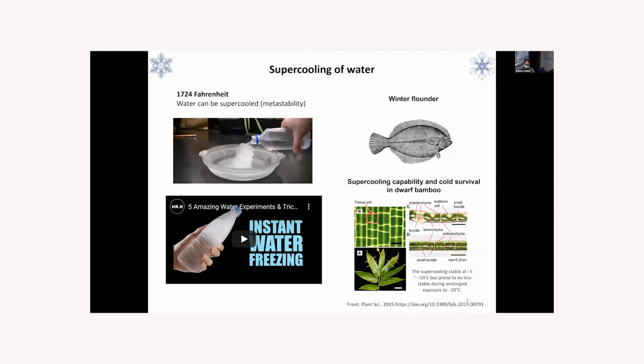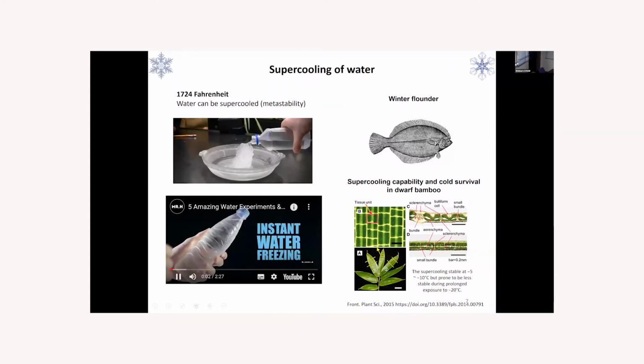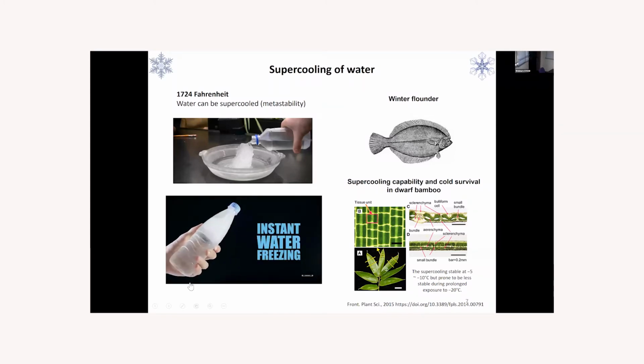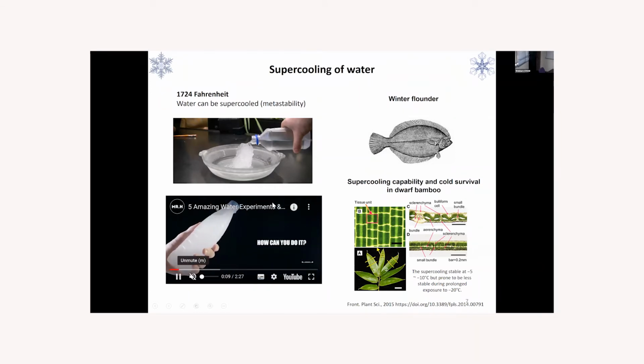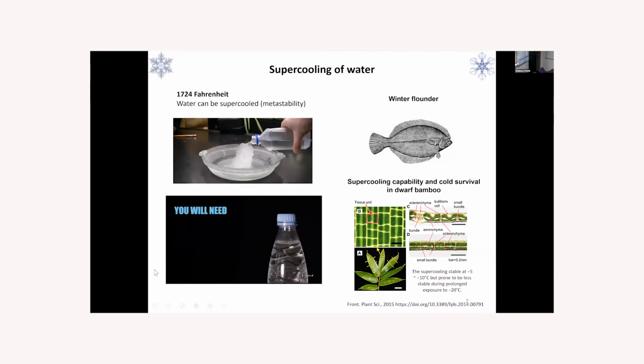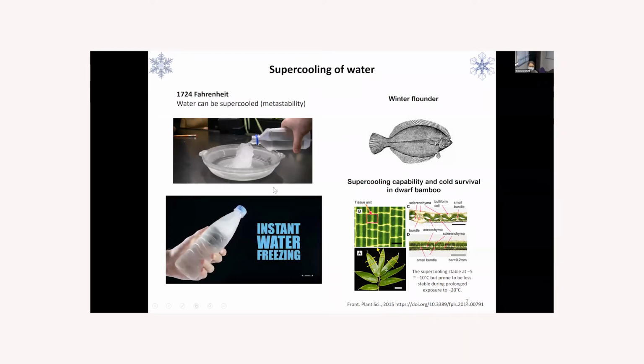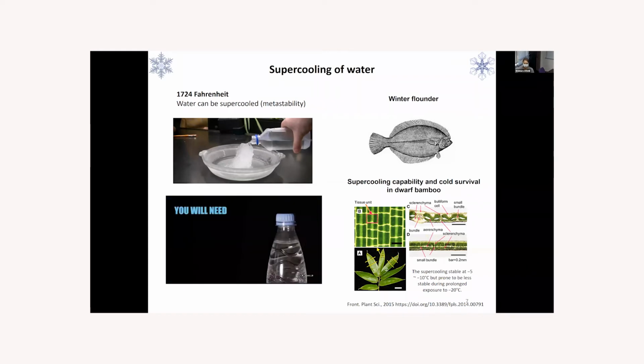So only after we induce the freezing by shaking or by contact with a surface, the water starts to freeze. And this is shown here. Okay, let's see it again. The water was supercooled, and just by the shock, we induced the freezing.